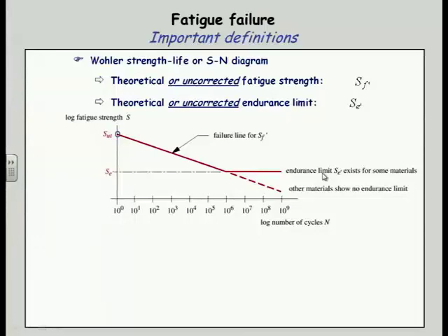And the most common test is called a rotating bending test. So a fellow named R.R. Moore came up with a clever design for the fixture that, by hanging weights, he can put a bending moment on this thing without actually touching the middle of it. You don't want to put a side force on it because that's going to give you funny business. So he loads it from the ends with a moment like this, and he spins it, and he runs it at 1725 RPM because that's the speed of an AC motor.